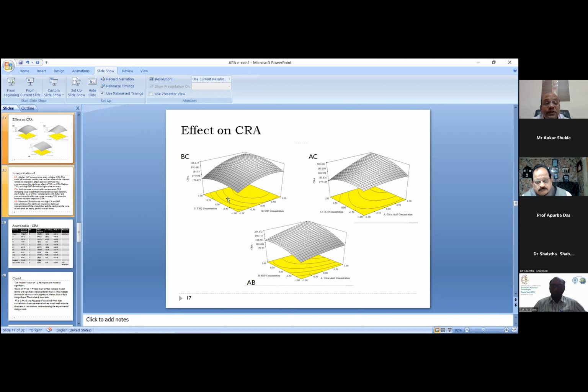In the case of TiO2, there is not much improvement in crease recovery angle, right? And here also we find that as the crease recovery angle increases, there is an increase in the citric acid concentration. TiO2 somewhere in between is quite okay. If you see the contour plots below and extrapolate, then probably with further citric acid concentration increase, there will be a further increase in the crease recovery angle. Coming to the third one, the citric acid concentration again positively influences CRA, and the SHP. If you combine both these, it is gradually increasing. And if you see the strip, you have the maximum CRA when you have the highest concentration of SHP and the highest concentration of citric acid.